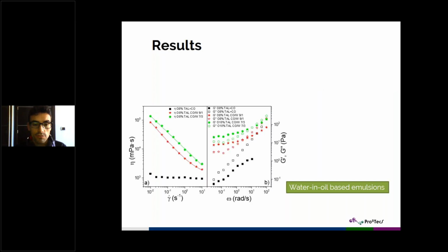And finally, just to see some rheological results of these emulsions, we can see that if we have no water, we have really low viscoelastic function and even a Newtonian behavior for the viscous values. While as we increase the content of water, we obtain higher both viscoelastic function and viscous values. We can add up to 30% of water, and the system is still stable. However, after we add 40%, finally we get two phases separated, so our emulsion is reverted.